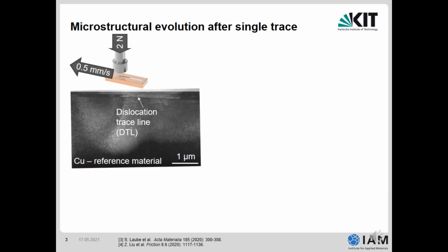Here you can see a STEM image, and the lamella was cut parallel to the sliding direction in the middle of the wear track. Here on top you can see a protective platinum layer. This is necessary for the lamella preparation in the focused ion beam. Here on top you can see these two horizontal lines which were caused by the tribological loading. We call them dislocation trace lines.